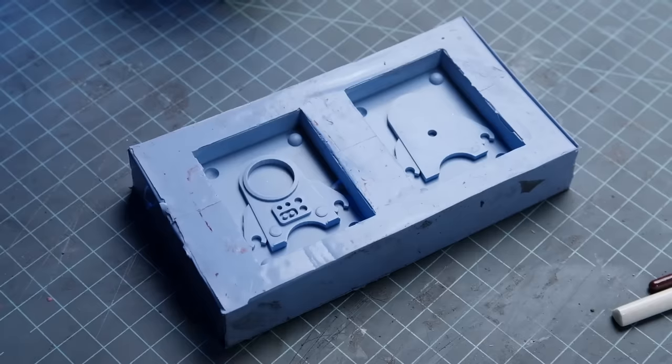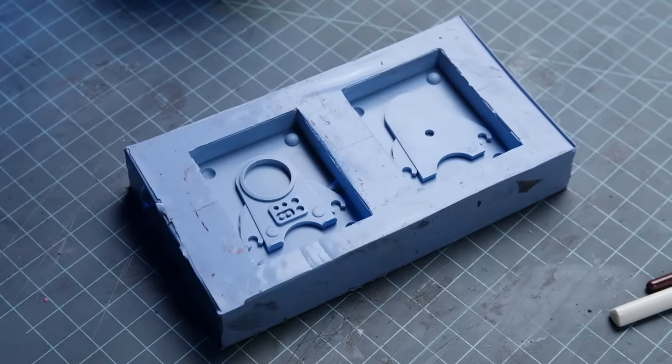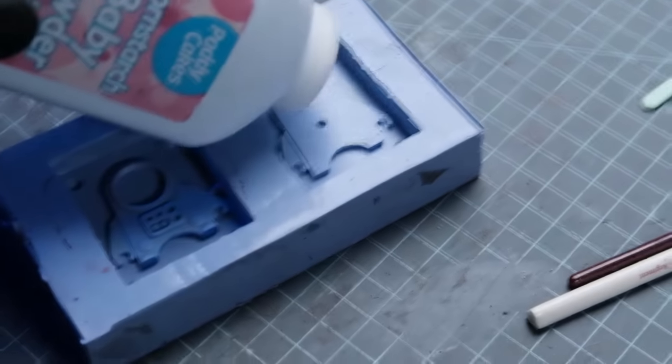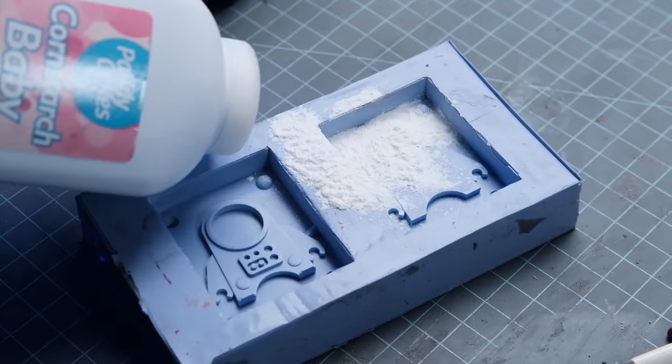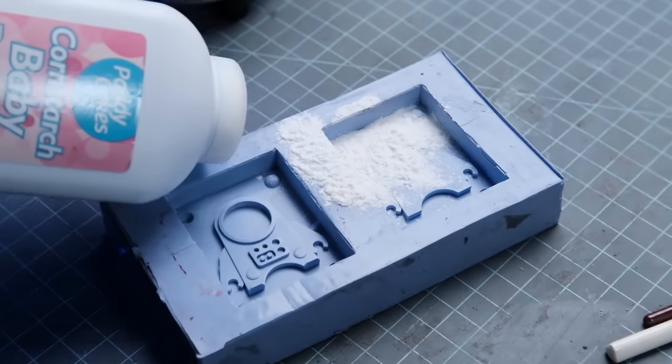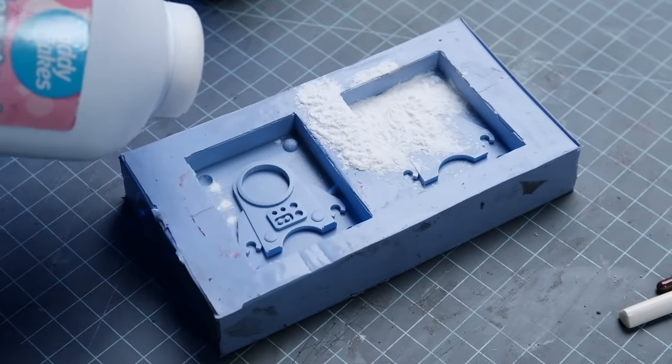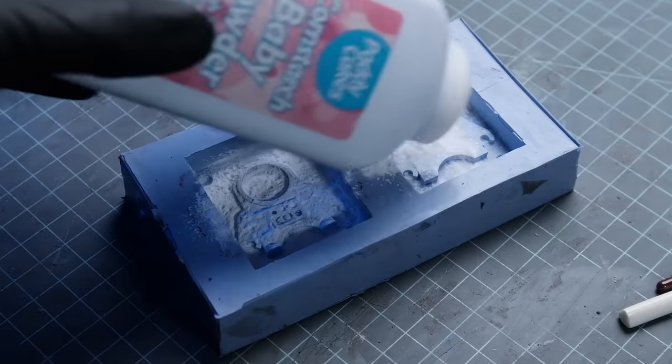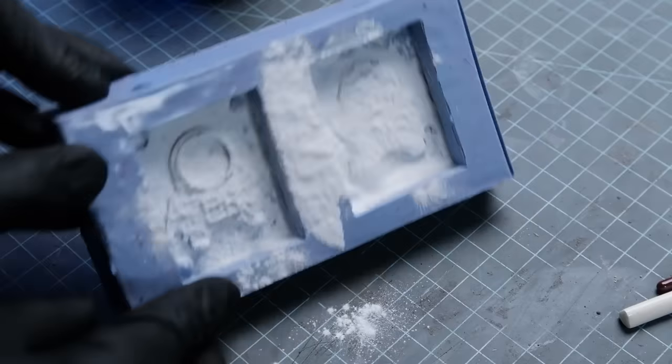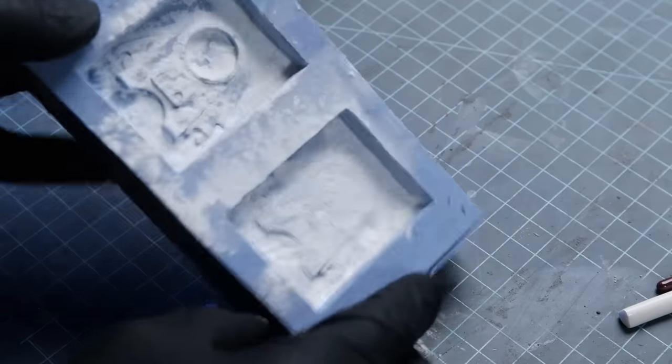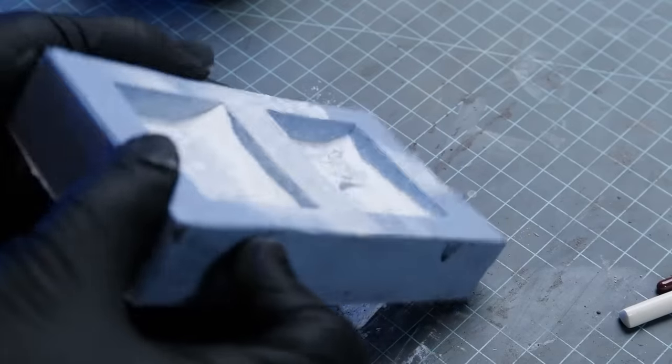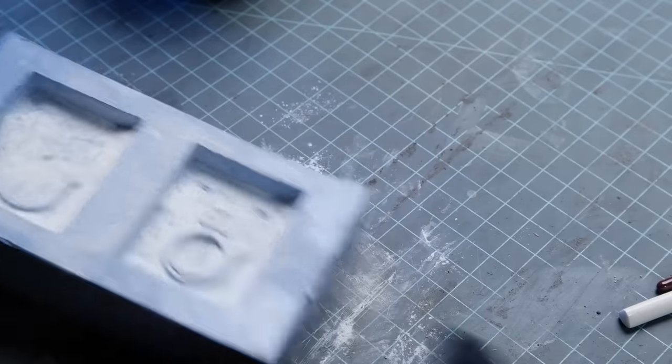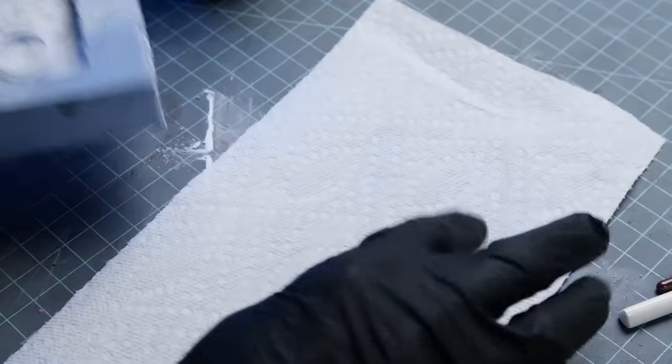Even though this silicone is not designed specifically for high temperatures like Mold Max 60, silicone is very decently heat resistant. For anybody interested, this particular silicone is Smooth-On Oomoo. It's not as tough as platinum cure silicone, but because it's tin cure silicone, you can make a mold of the original resin 3D prints without worrying about cure inhibition and getting a goopy mess, and no acrylic spray sealant required.